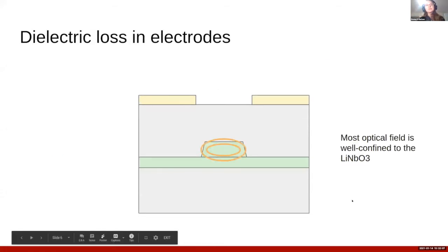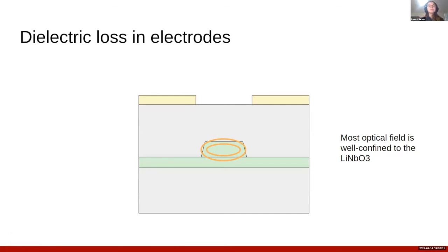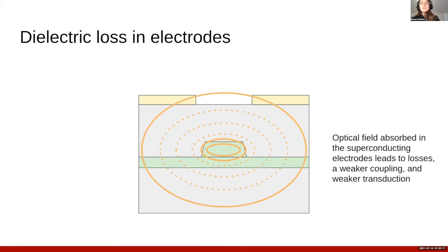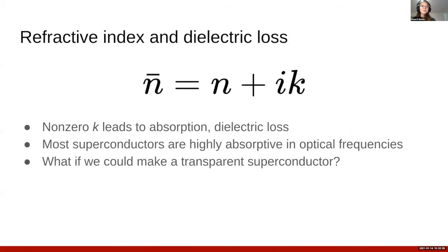Most of the optical field will be really well confined to the lithium niobate, but as always, some of the evanescent field is going to persist in our dielectric. Any optical field that's absorbed in these superconducting electrodes will lead to losses, as is discussed, I think, in an earlier talk. And that leads to weaker coupling and weaker transduction. So, how can we fix this?